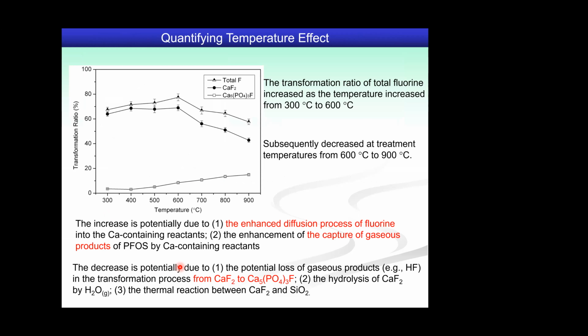Okay, go back to the optimization process. In fact, if you really can control your temperature around 600 or 700 or even 500 degrees Celsius, it's actually good enough for you to stabilize your fluorine quite nicely to about 80%. And when you go up above 600 degrees Celsius, then the calcium fluoride reaction pathway is actually not that efficient anymore, and is replaced by the relatively more efficient stabilization route by the fluoroapatites.